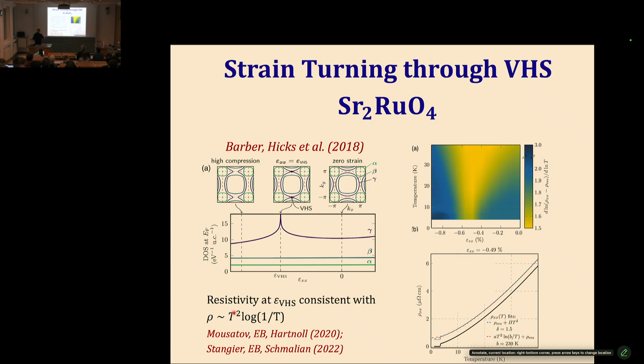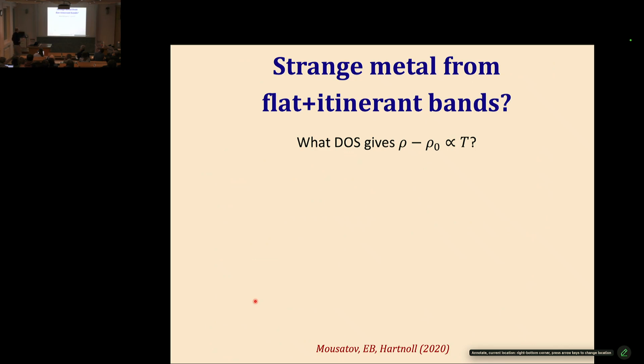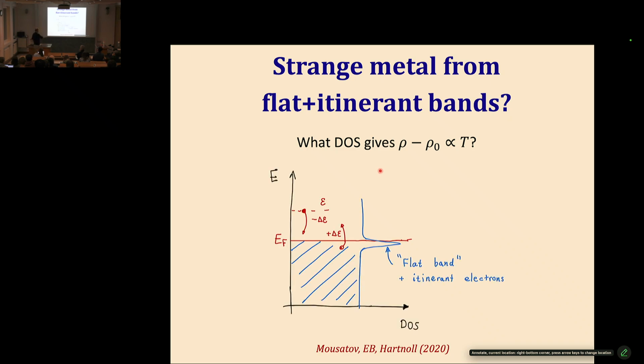But you can ask, suppose I want to explain a power law behavior with an exponent smaller than 1. In particular, I want to explain linear in T resistivity, which is very different from this thing. What kind of energy-dependent density of states do I need to get that? That's not a hard exercise, using basically the same reasoning. It turns out that what you need is basically a delta function in the density of states.